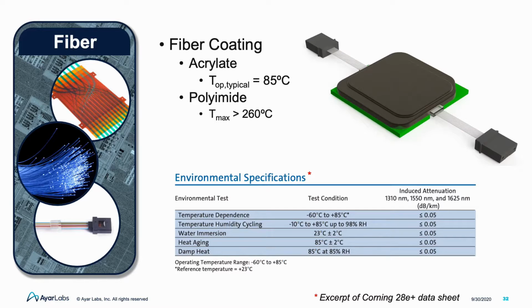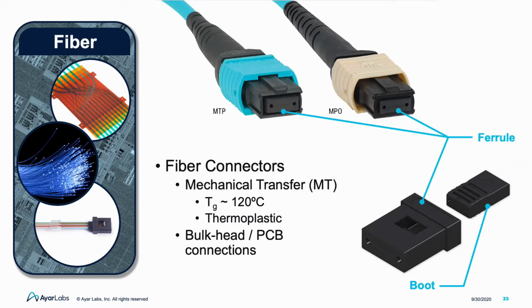The typical acrylate coating is only rated for a maximum operating temperature of 85 degrees C. Here we see a datasheet excerpt from a common optical fiber. Fiber vendors have engineered higher operating temperature coatings, including both acrylates as well as polyimides. The challenge with polyimides is stripping. Polyimide is such a good material that it's hard to strip from the fiber, a process that is required for some assembly steps.